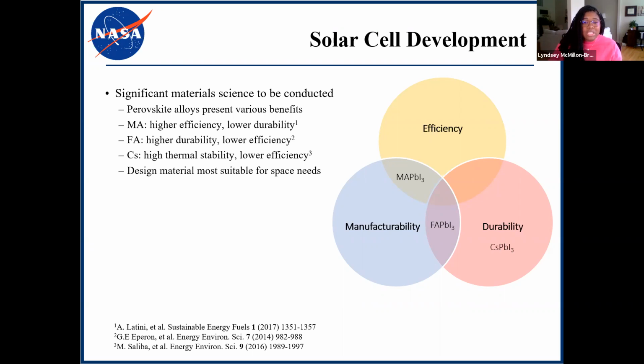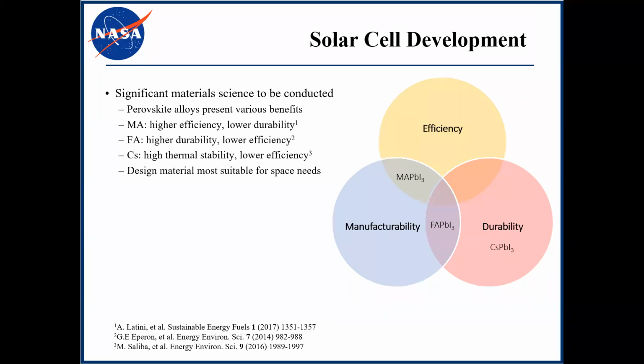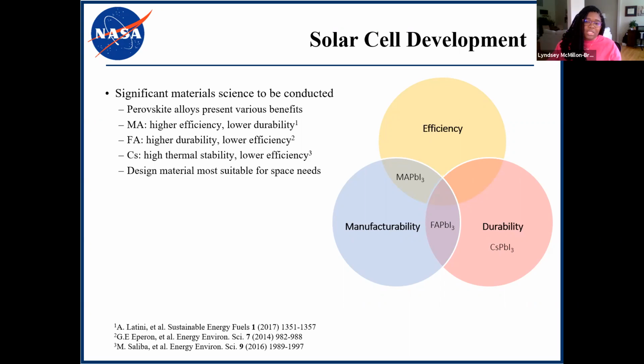And then when we consider cesium lead iodide perovskites, they exhibit high thermal durability, but a lower efficiency. And fully inorganic cesium lead bromide has really good thermal stability, but it doesn't have an ideal band gap. Cesium lead iodide has a more suitable band gap, but it also crystallizes in the yellow phase at room temperature, and the black phase tends to only be stable at much higher temperatures, like temperatures above 300 C.